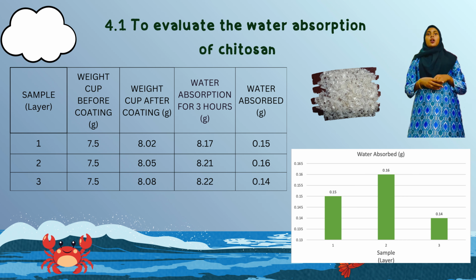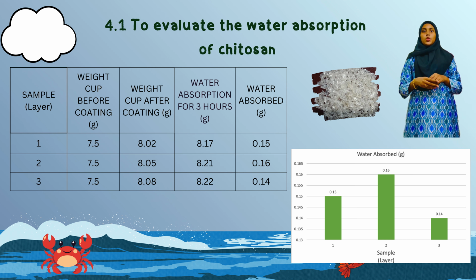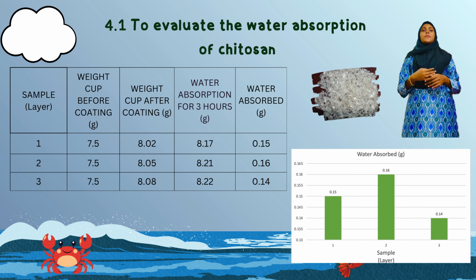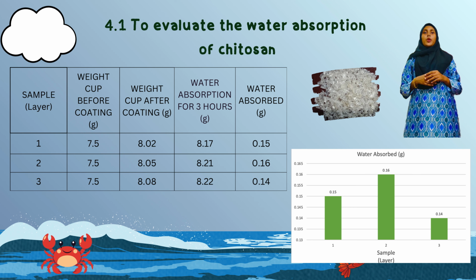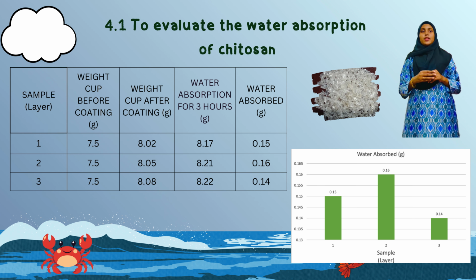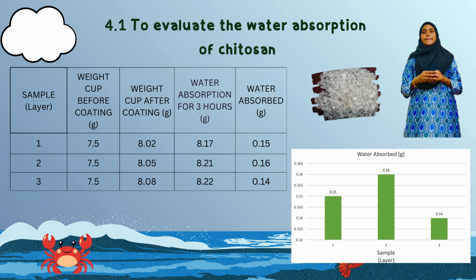Okay, this is the data of evaluation of the water absorption of the chitosan. So we have 3 samples. So weight of the cup before coating is equal, which is 7.5 for each of the samples. Weight of cup after coating for sample 1 is 8.02, for sample 2 8.05 gram, and sample 3 8.08 gram. So water absorption for 3 hours for sample 1 is 8.17 gram, for sample 2 8.21 gram, and sample 3 8.22 gram. So the total water absorbed for sample 1 is 0.15 gram, for sample 2 0.16 gram, and lastly sample 3 is 0.14 gram.